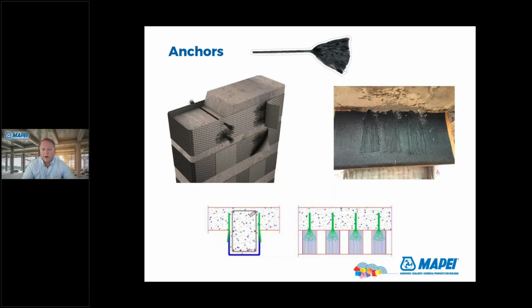That is an area where the development length is typically not long enough to develop the strength, and so it'll typically debond right up at the top there. So some of these FRP anchors are used where they'll drill into the slab above or to the beam, epoxy that hole, and then stick these FRP anchors and fan it out to help increase that development length and keep it from debonding.